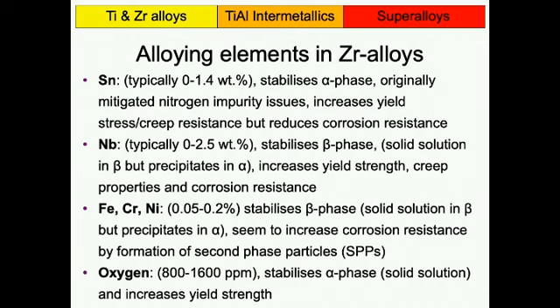Actually, that statement is not entirely correct. Niobium, I don't know why I've never noticed that mistake. Niobium has a limited solubility in alpha. Tin can be retained in solution in the alpha phase for the kind of amount of tin that is typically added. Niobium, there's a lot of discussion about how much niobium can really be dissolved in the alpha phase. Typically, people say up to 0.5 weight% of niobium, but actually, some of the work we've done more recently suggests it's much, much less.